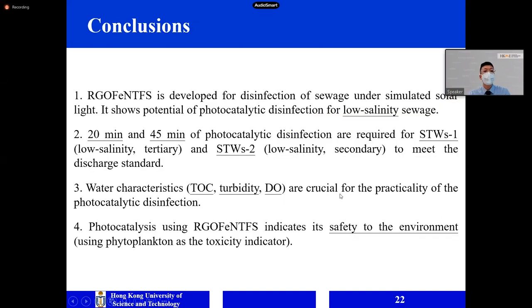Here is the brief conclusion. For the first part of this study, we developed this type of photocatalyst with enhanced efficiency for photocatalytic disinfection for low salinity sewage. And for the first type and the second type of sewage, it takes around 20 minutes or 45 minutes to meet the discharge standard under the irradiation of simulated solar light. And also the water characteristics, especially the TOC, turbidity and the DO, have crucial impacts on the practicality of this technology. And finally, by using the bioassay with the phytoplankton as the toxicity indicator, we can see the safety of using this photocatalyst in real wastewater.